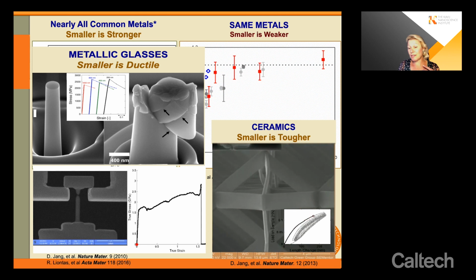Now, to show you the deformation of a single unit within one of the nano architectures that I showed you, this is made entirely of a very, very brittle ceramic, titanium nitride. And you can see that these beams are bending. Now, if you were to calculate the stress that's operating in these beams, it exceeds 1.5 gigapascals. No ceramic is supposed to stay intact when you're applying that much tensile stress to it. This one is not only staying intact, but it's doing it over multiple cycles.